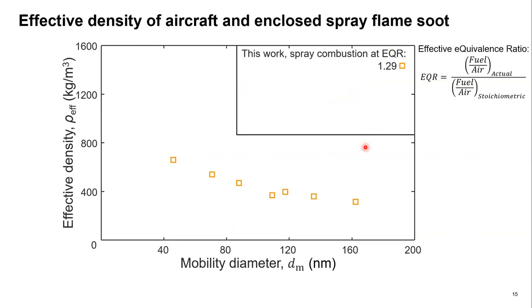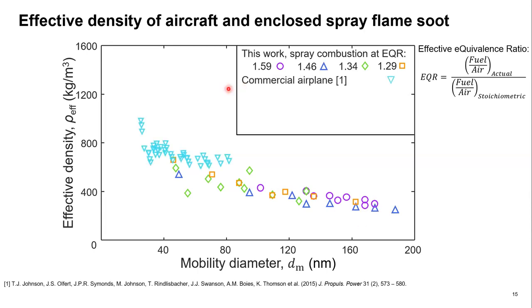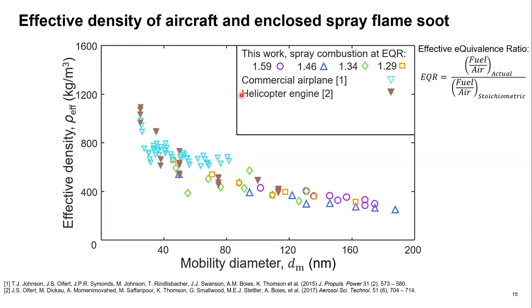The same data can be used to estimate the effective density of the soot. Here on the x-axis, we have the mobility diameter, and on the y-axis, the effective density. Again, starting at the leanest equivalence ratio of 1.29, 1.34, 1.46, and finally 1.59, we see again that there is no significant difference between the different equivalence ratios. But comparing to data from a commercial aircraft and a helicopter engine, what we see is that our data continue the trend that we see from the real aircraft soot and thus are in good agreement with the literature.